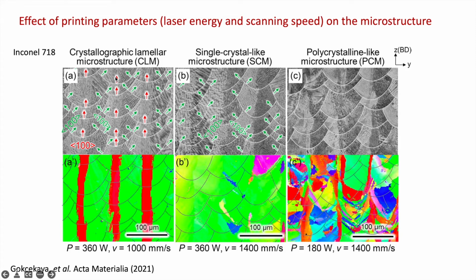At the center of the melt pool, these are 001 grains if you view from the top. If you look at the side of the melt pool, although those grains are growing in the 001 direction, if you view from the top, these are close to 011 direction. The 011 direction in EBSD is green. That's why you see a lot of green in the previous slide. One more thing you can learn from the slide is by carefully controlling the spacing of the melt pool, you can create the lamellar microstructure as shown in A, as well as the single crystal-like microstructure in B.